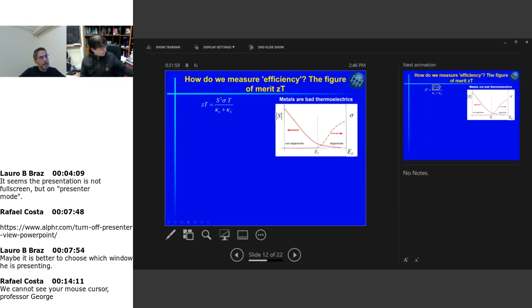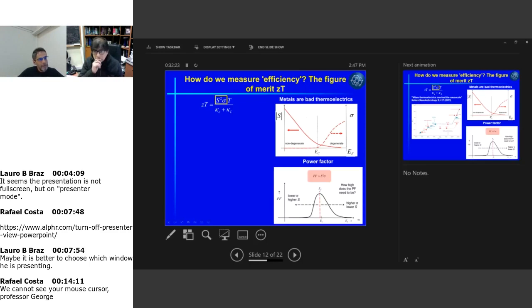As I mentioned already, a metal, and a heavily doped semiconductor behaves as a metal, has good conductivity, but a poor Seebeck coefficient. On the other hand, a non-degenerate semiconductor is going to have a large Seebeck coefficient, but a very low conductivity. So you are in a bind here, because the product S squared sigma, which is called the power factor, is going to have a sweet spot exactly where they cross, or around the region where they cross. For a semiconductor, it's placed around the bottom of the conduction band.